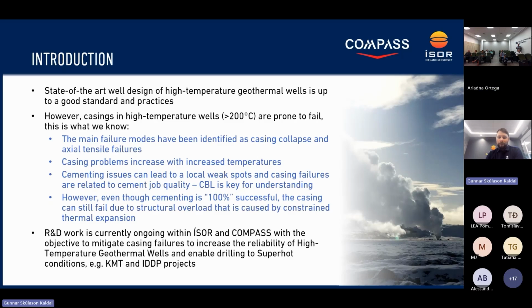Cementing issues can lead to local weak spots in the casing, and this cement quality is really important for the casing to survive. So CBL logging or cement bond logging is key for understanding the structure before it heats up. And even if the CBL looks fine, we have also seen some problems. Even though the cement seems to be perfectly fine, if there are some liquids behind the casing that can expand, they can create problems for us.